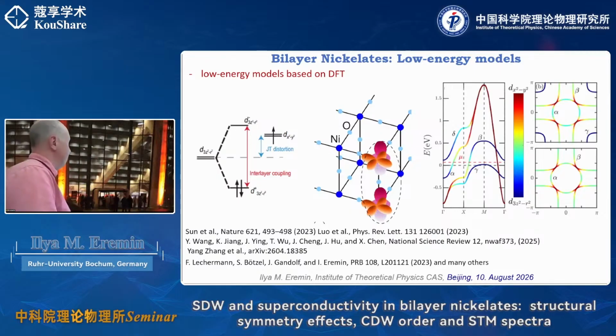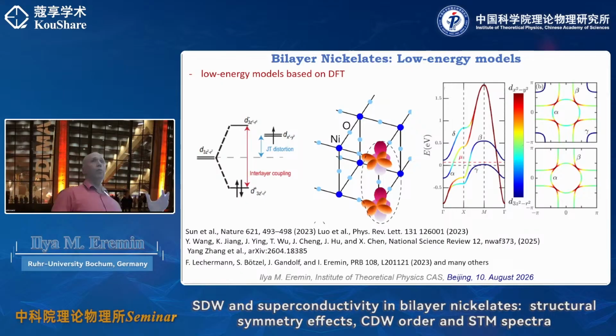So that's, let's say, a model that is considered to be the low energy model by the majority of the community. Basically you have an eg manifold, so it's d7.5 or d8 if you assume that there is also oxygen involved for the ligand hole, and then you're dealing with the eg manifold, so you have the dx²-y² and the dz² orbitals sitting on the nickel, and then because of this apical oxygen, you have a strong hybridization.